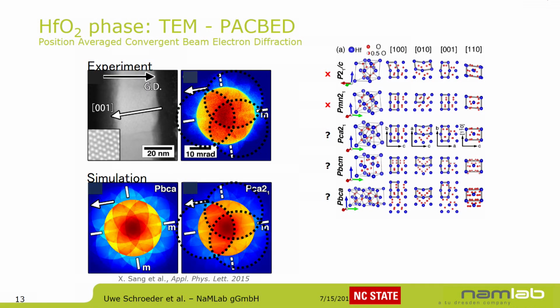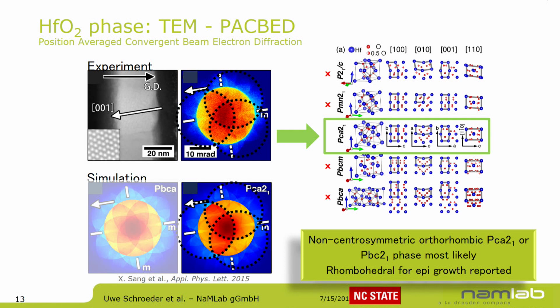From the phase point of view, we had some discussions in the very beginning about what the phase of the hafnium oxide is, and here's some work from NC State. Dr. Sang looked into this by electron beam diffraction, by CBED. You take the electron beam of the TEM and look at the diffraction pattern, and this is the experimental result, and you compare this. So he simulated, for all the known structures for hafnium oxide, the according pattern, and the best correlation was found then for this Pca21 or Pbc21 phase of the material. And if you look now in the literature, there is also the rhombohedral phase shown for epitaxially grown films of hafnium oxide.